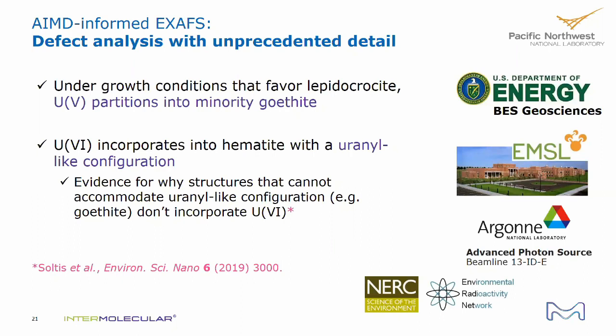Oh, wait, you have a single absorber? How is that different from bottom up? Well, the difference is that instead of having fit parameters for each individual shell, we end up fixing everything. We fix the interatomic distances, we fix the disorders.